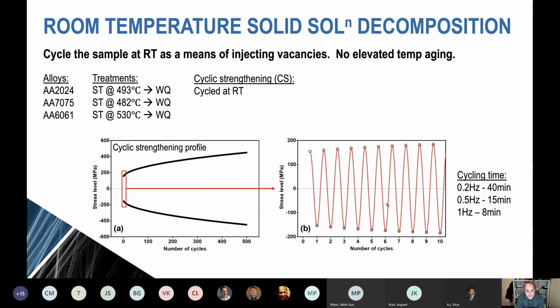And so we've tested this on a whole range of model aluminium alloys, but also commercial alloys. And I'll show you here, these are 3 commercial alloys. 2024, an aluminium copper magnesium alloy, 7075, an aluminium zinc magnesium alloy, and 6061. And these are probably the 3 most common aluminium alloys that are used. And so we've taken these commercial materials, we've solution treated them at elevated temperature and then quenched. And so they start as a full solid solution material.